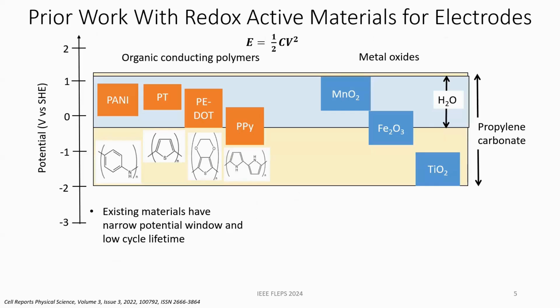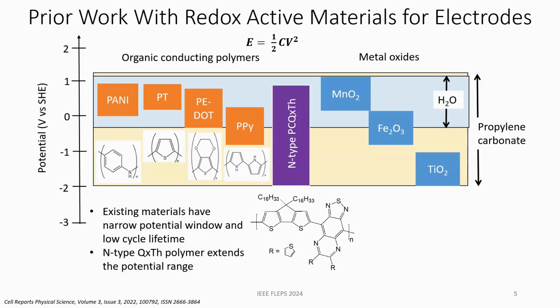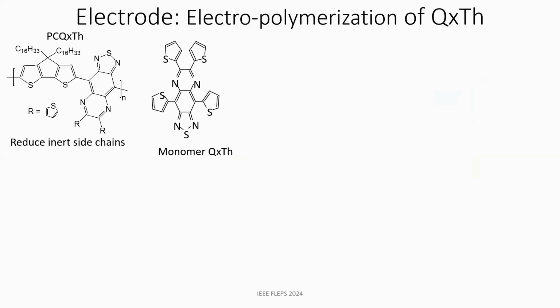Before we move to the structural component of the electrodes, there are two ways to increase the energy density, and that's increasing the capacitance or the potential window. Prior works have used organic polymers and metal oxides, and these have a high capacitance but a lower voltage window, which reduces the overall energy output. They also have a low cycle lifetime. Our group has worked with the N-type QXTH polymer in the past. This has open shell redox states, and it has a lower capacitance overall, but it has a high potential window because we can extend into the negative range here. So we have a good polymer to use, but we can still improve the capacitance.